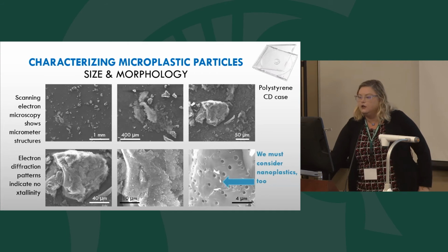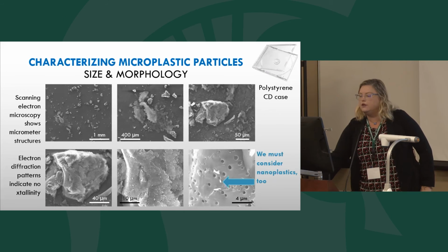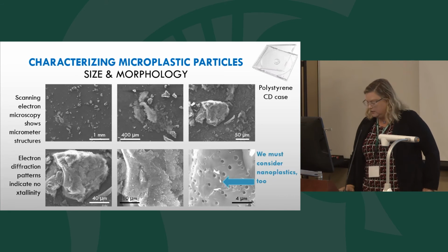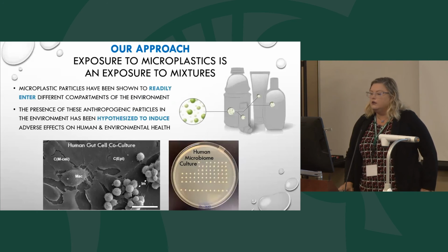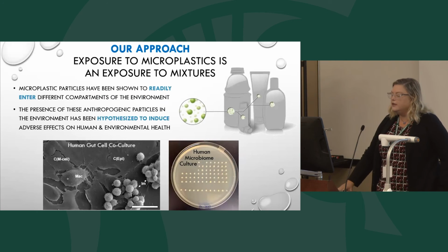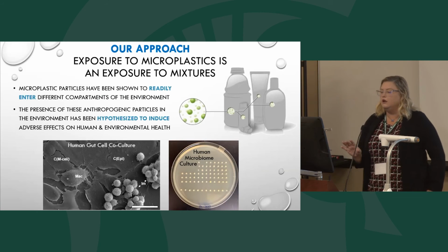And of course, again, when you do EDAX on these smaller fragments here, they're the exact same chemical composition as the background, telling you that these are the polymer samples. They're just in a separate nano-sized range compared to the background microplastic that is larger, closer to 50 micrometers in size.